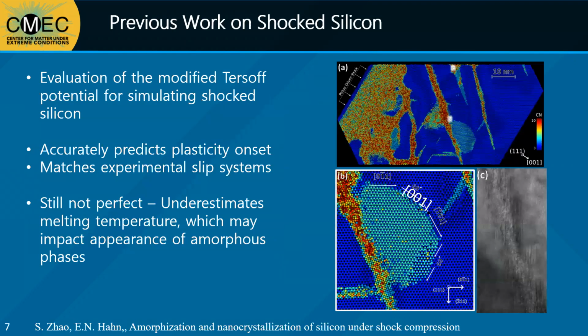The modified version of the Tersoff potential that we use in our silicon shock simulations was developed by Kumagai et al. and compared against several other silicon simulations in previous work by Shiteng Zhao and Eric Hahn. The modified Tersoff potential predicts the onset of plasticity at 0.82 kilometers per second. This compares well with experimental data, whereas other potentials such as the Ehrhart-Albe or Stillinger-Weber potential require piston velocities of up to 2 kilometers per second to induce plasticity.